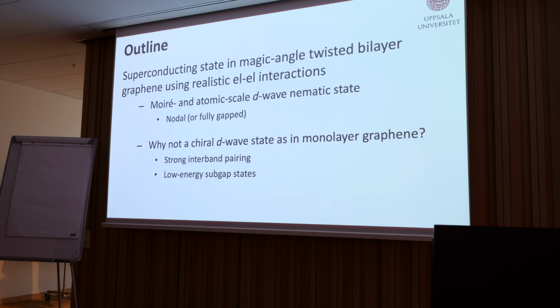So if you do monolayer graphene and you do a very similar or the same approximation for the pairing, you always get the chiral d-wave state. So one question that we always had is, why isn't twisted bilayer graphene giving us the chiral state? So I'm going to try to show you what's happening in short stories. There's very strong interband pairing in twisted bilayer graphene, and the chiral states suffer from low energy subgap states. And neither of these happens in doped graphene, but it happens in twisted bilayer graphene.